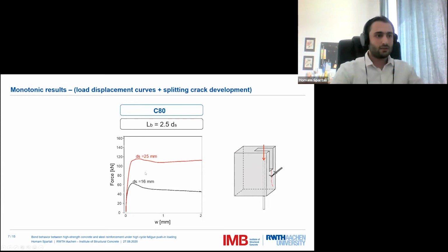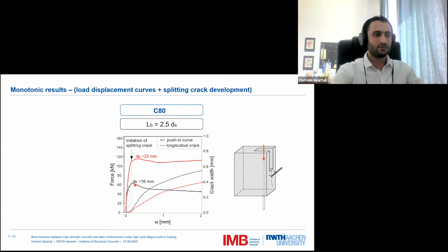So at some point of the loading, we will observe this splitting crack that comes along the bond zone. Let's mark this point with this dot in this experiment and this dot in this other experiment. And here we can notice something: by the emergence of the crack at this point, the bond stiffness directly decreases, but the force will keep going up until we reach the peak. And after the peak, we will see a deterioration in the bond resistance with the rapid increase of the width of this crack.